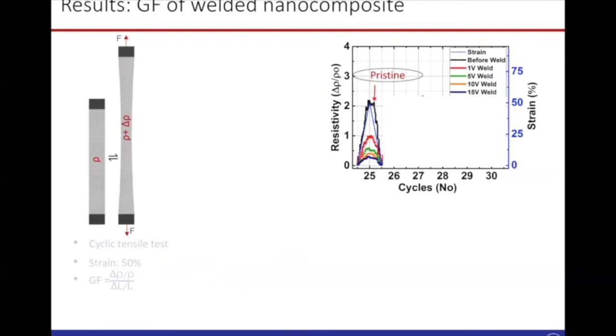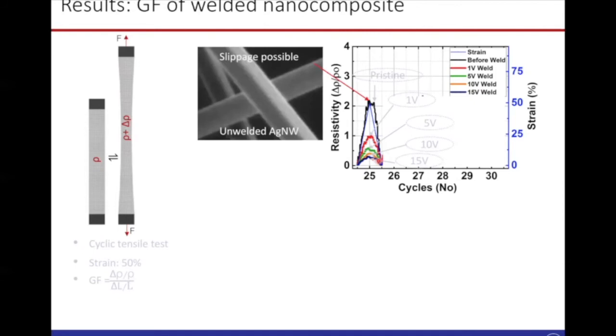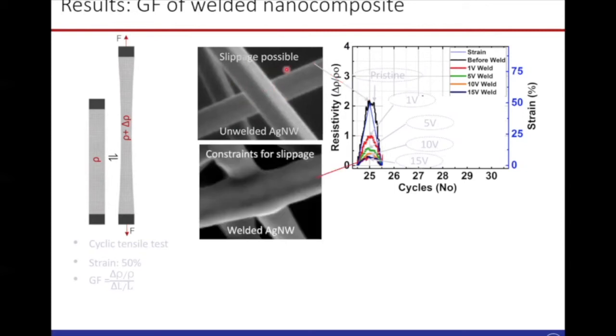Here the blue curve is strain and the black curve is the change in resistivity. In the pristine condition, you have a large change in resistivity. It means the behavior is more like a sensor. As you apply 1 volt and then 5, 10, 15 volts, at the end of the welding, you can see the gauge factor suppressed and it approaches close to 0. And this is exactly what we need for a nanocomposite to behave as a stretchable conductor. So what happened here? If you look at this image of silver nanowire, before welding, the junctions are loosely connected and slippage is possible. And after applying the voltage, the junctions are modified. And of course, you apply constraints for slippage on many of the nanomaterials. And this could control the gauge factor.